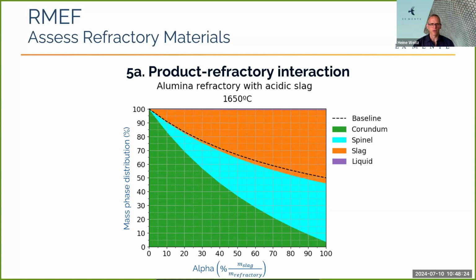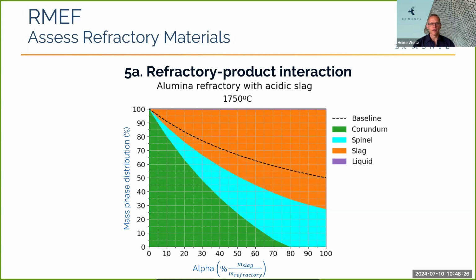And then we can just increase the temperature gradually. And at this point, we can see that a significant amount of your refractory material starts to melt at this temperature. So at this point, it would not be feasible to use the material.